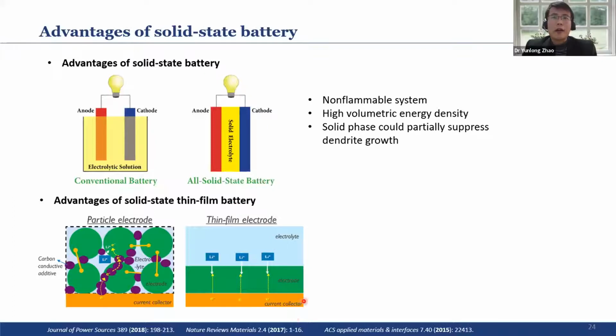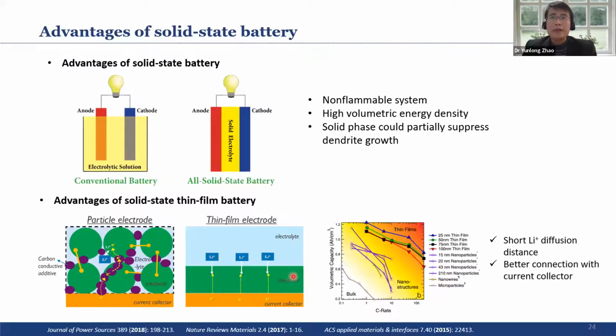So everything can be evaporated, for example by sputtering, even including the anode material, cathode material, and the electrolyte. And they are quite thin, usually from hundreds of nanometers to even several microns. So they have a very short ion diffusion distance and very good adhesion to the current collector, with a very smooth interface.